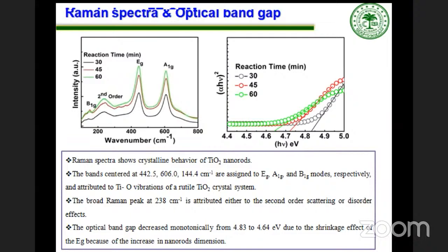And to calculate the optical band gap, we performed UV-visible absorption spectroscopy, and we calculated from that, and it is plotted in this diagram. The optical band gap for the 30 minutes sample was observed to be 4.83 electron volt, and it decreased monotonically with the increase in dimension of the nanorods.